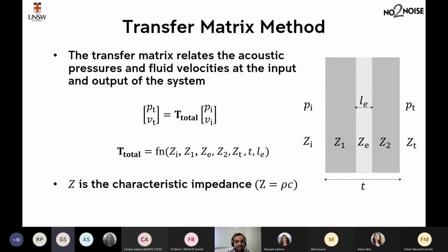So a transfer matrix actually relates the acoustic pressure and fluid velocities at the input and output of the system. So once we know the density and once we know the dimensions and material properties of different layers, we calculate the transfer matrix for each layer, and then we multiply them, and then we get this total transfer matrix, which is just a multiplication of transfer matrices for different media. So if you see here, here you also have the impedance of the medium on the incident side and transmission side, right? And here Z is actually the characteristic impedance of the material, which is just density times speed of sound in the medium.